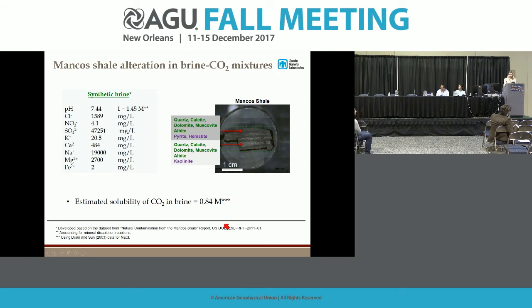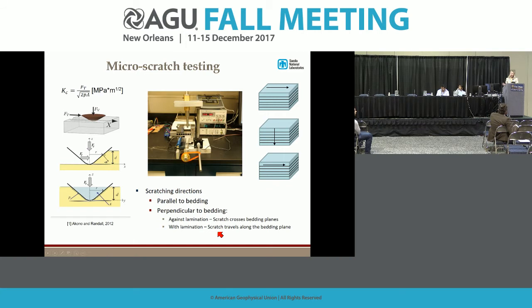So for our high-pressure CO2 reactor. And now to micromechanical testing. We have been performing microscratch testing to characterize changes in mechanical properties of natural shale samples following the alteration by CO2. And what it does, we have a stylus that we're applying at a known force to the surface of the sample, and we drag it along, creating a scratch.